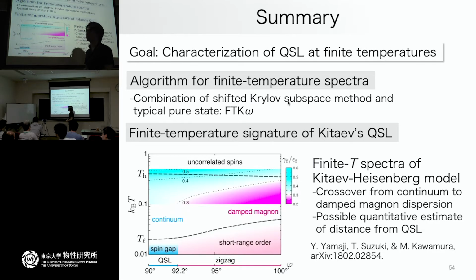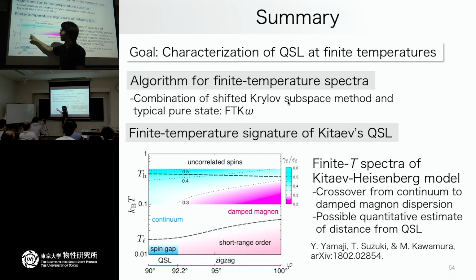And from this we can get rid of the finite size effect above this temperature. However, the criterion, which value is the proper value for the crossover, why 0.3? It's not so quantitative. But for example, if you look at the curve here, then around this temperature, this ratio has more or less a saturated behavior like this.